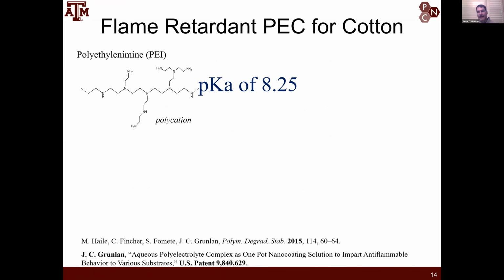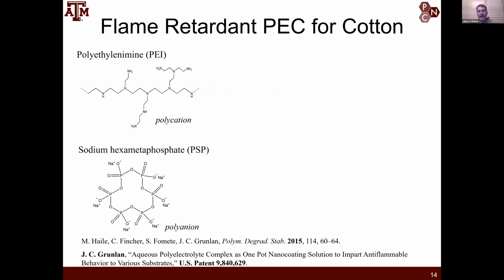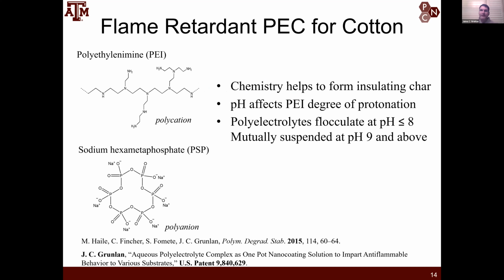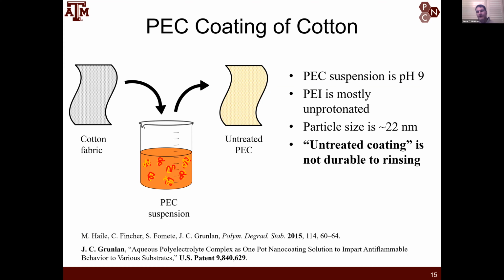The first is textiles. So cotton, of course, is the most used textile for clothing. And so we can use something like polyethyleneimine and pair it with sodium hexametaphosphate, but we keep it at a pH where they will not complex. I purposely keep PEI at a high pH so that it has low charge density. But then when I reduce its pH below 9, a complex will form because the charge density of PEI will increase.